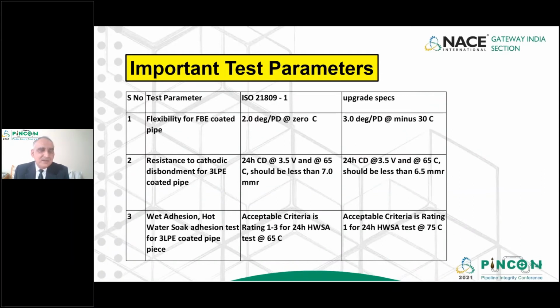Number two parameter is resistance to cathodic disbondment. This is actually a measure of simulation of how this corrosion protection coating will protect the pipe in field conditions. So there are again several specifications like CSA and ISO, and most commonly in ISO it's written as a 24-hour CD test at 65 degrees Celsius, which should be less than 7 mm radius. Our recommendation is to make it a little bit tighter and make it less than 6.5 mm radius, and it has been implemented in some companies.